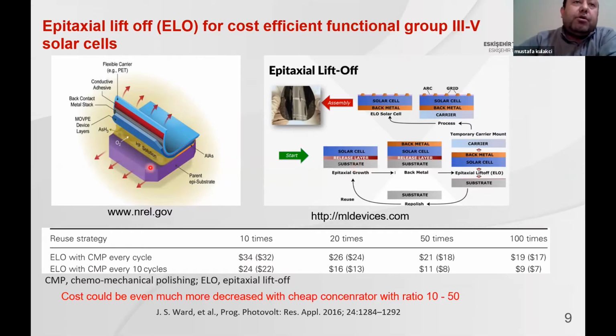In this scheme, you grow devices on a template, a high quality template, by using some release layer. Then after growth, you can take out this release layer, and you attach these devices to the flexible plastics. In most common case, you use aluminum arsenide as a release layer. Then by using some special solution of HF, you can easily dissolve the aluminum arsenide, and your device is not affected with this solution.